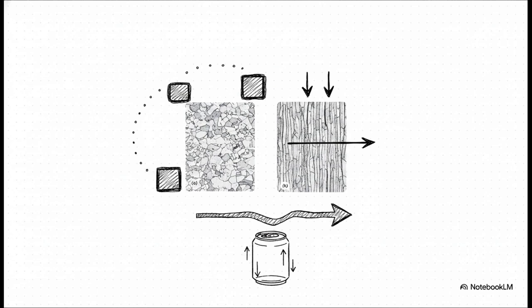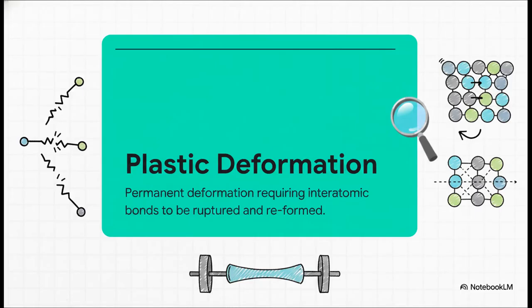If we zoom way in, say 150 times magnification, we can see exactly what's happening beneath the surface. In its original state, the aluminum has a grain structure where the grains are equiaxed. That basically just means they have roughly the same dimensions in all directions, kind of like a microscopic tiled floor. But after the can is formed, it's a totally different story. The grains themselves literally stretch out and elongate in the direction of the applied force. So that massive shape change of the can that we see with our own eyes is a direct result of this intense microscopic stretching.